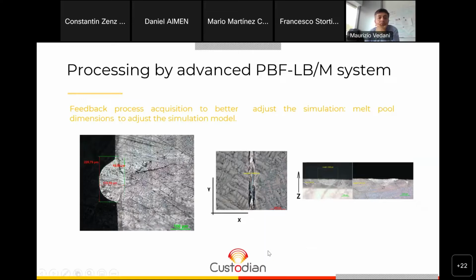As I was saying before, some information about the process was acquired and studied to feed back to the simulation model to adjust the thermal cycles in the simulation model. For instance, this is one of the tests that we did for CM247 low carbon. Basically, here we added powder layer by layer, and in the last layer we added a powder bed again, but we just melted a single track. The reason for this experiment was to measure the weld depth and weld track, the dimensions and the geometry of the track, so that it can be replicated by the simulation, right? And that's all from my side.